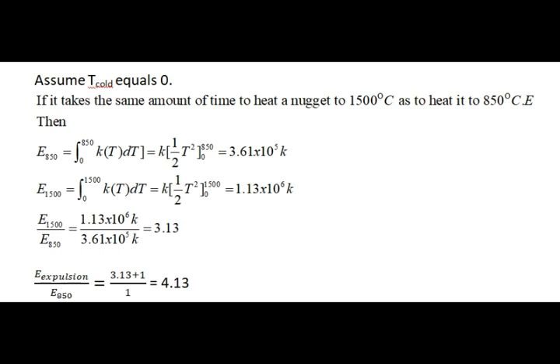any desired temperature. This shows the energy needed to heat the faying surface from 0 degrees Celsius to 1500 degrees Celsius is 3.13 times the energy needed to heat the faying surface from 0 degrees Celsius to 850 degrees Celsius. Assume the latent heat energy used to melt the metal equals E850. Then it takes 4.13 times the energy to make an expulsion weld than an 850 degrees Celsius weld.